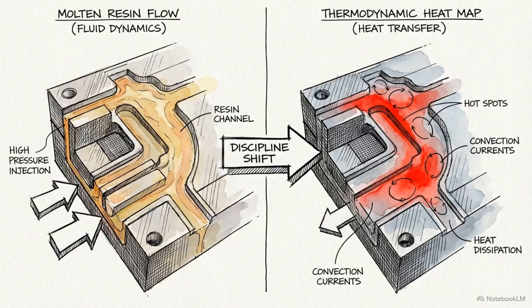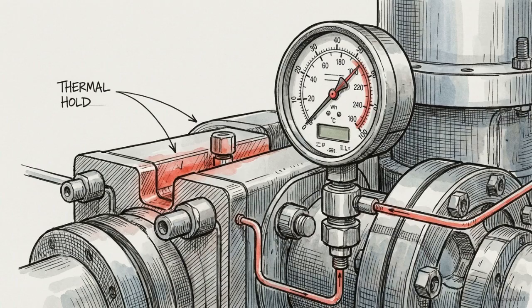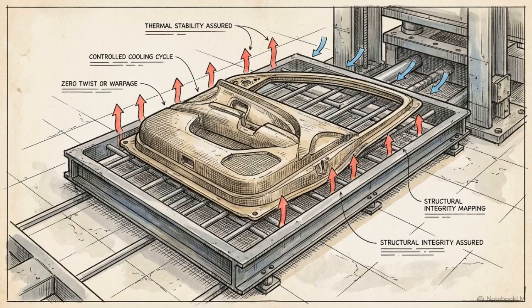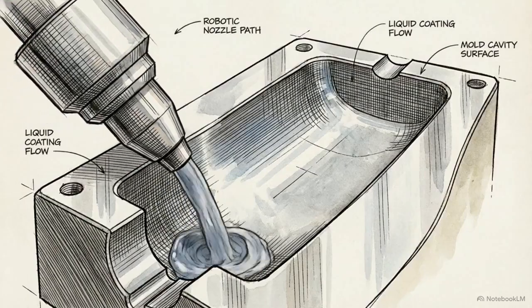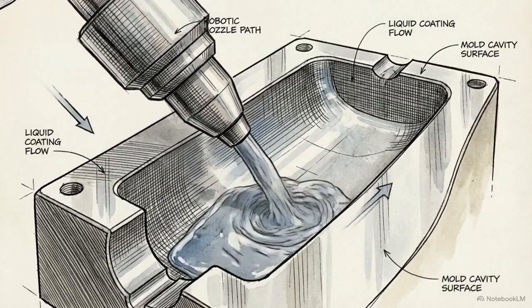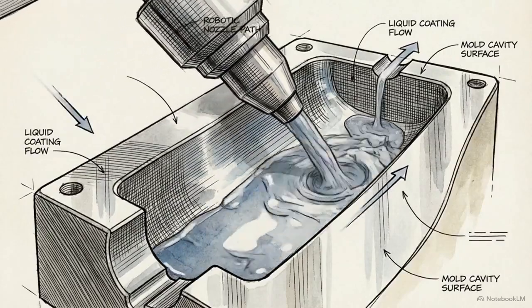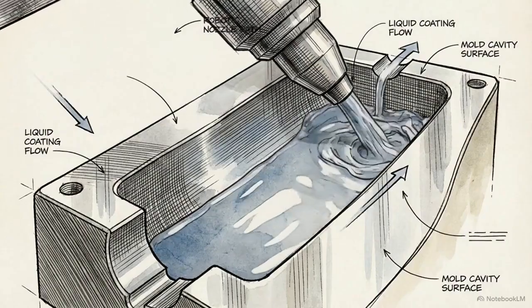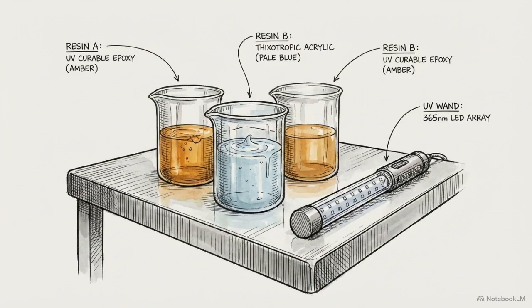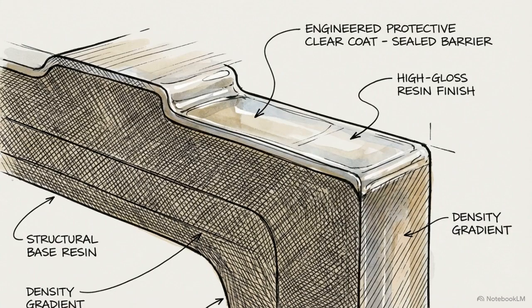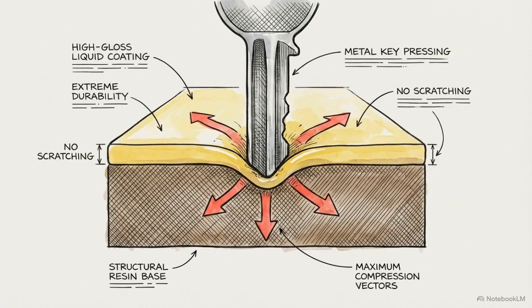Moving from thin IML films to thick IMD barriers forces a profound change in discipline. The focus shifts entirely from managing fluid flow to strictly policing thermodynamics, simply to prevent the part from destroying itself as it cools. In-mold coating, or IMC, discards solid films completely. Instead, specialized liquid chemistries are automatically dispensed directly into the open mold cavity space. These systems utilize thermally curable resins, UV curable formulations, and engineered polyurethanes designed for highly specific mechanical properties. Because these liquids cure in place, IMC generates a continuous engineered protective layer that vastly outperforms the scratch and chemical resistance of standard IMD films.